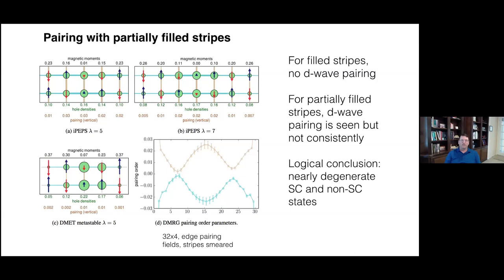What about superconductivity? Well, there's lots of results that I could show, and it's a little bit hard to pick out the pieces. This shows a little bit of what's going on. Let me just point out one particular thing. The scale that shows the pairing in this DMET calculation is much lower than the scale that is shown here. In particular, in between the stripes, it's particularly low.